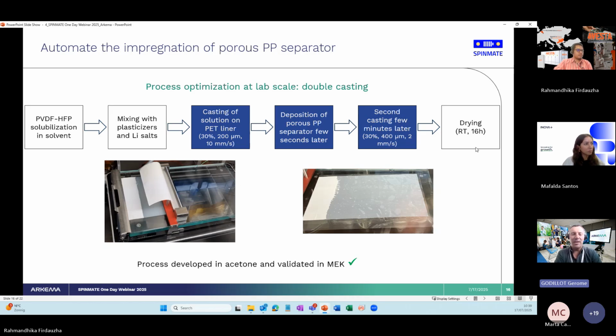Because we made some adjustments to the solid content of the solution, the coating height, the coating speed, and so on, we finally got a result that looks okay. The bubbles are only in the PP protective layer, so there's no bubble at the end. That was the main target. So we have something homogeneous, which is transparent because the porosity of the separator is filled with material that has the same refractive index. The white part you see on the left is the not impregnated part, which is the white porous PP separator.